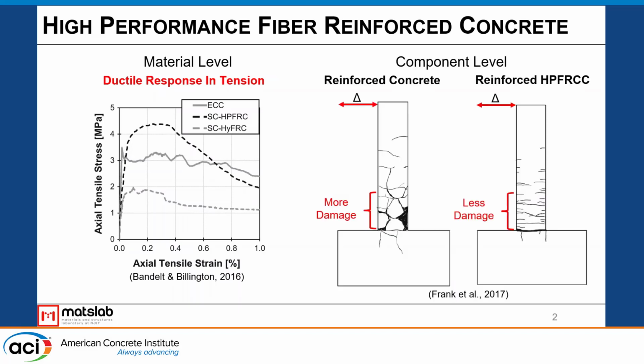When we reinforce these materials with steel, we typically see enhanced performance at the component level. To illustrate that concept, we have here two cantilever beams subjected to cyclic lateral loading. In the reinforced concrete beam, there's more spalling, the crack openings are much larger, and just generally there's more damage at the base of the component. In contrast, in the reinforced HPFRCC beam, we have finer crack openings, more distributed cracking, and overall less damage at the base of the component.